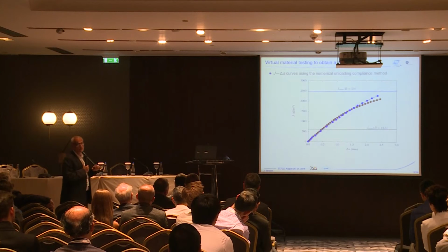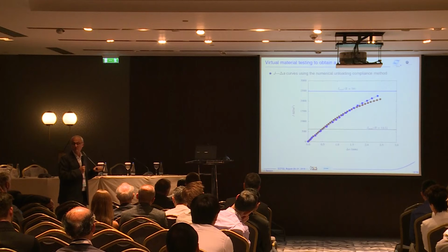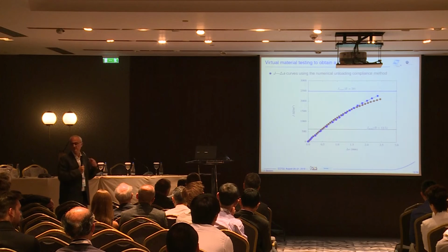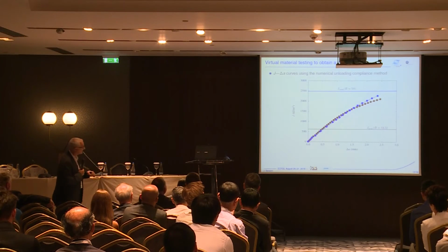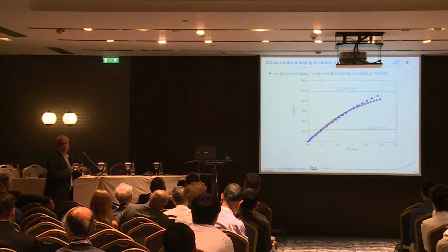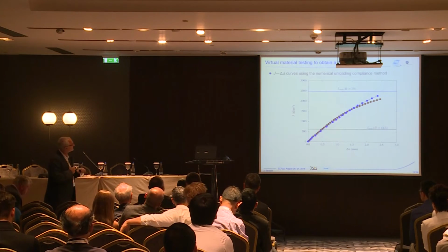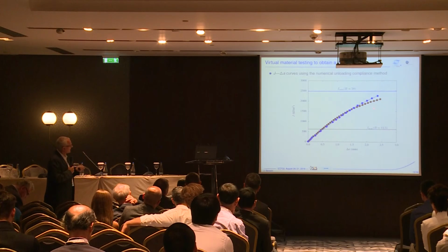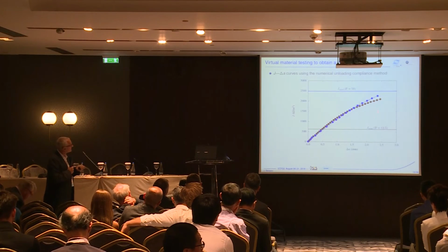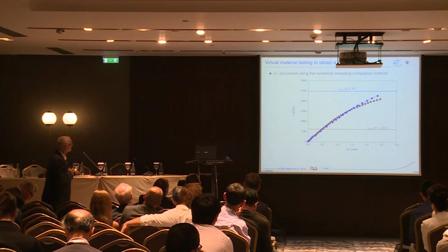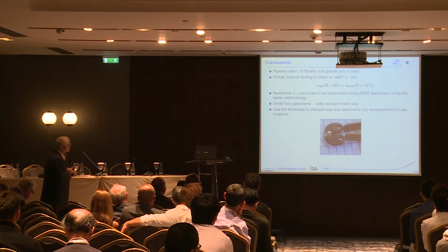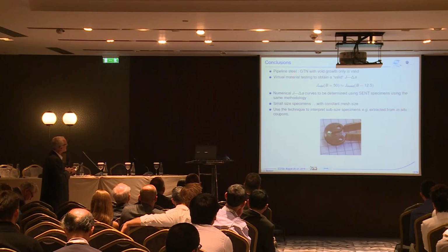What I did not really expect is that the difference between the two specimens would be so small. I'm quite surprised, so I have to repeat that, maybe do a CT100 and do the same kind of job on SENT. But if it's true, if I can confirm that, that's somehow good news, because it's very close, and the CT12.5 gives you some kind of lower bound, which is on the safe side from an engineering point of view. So, conclusions.